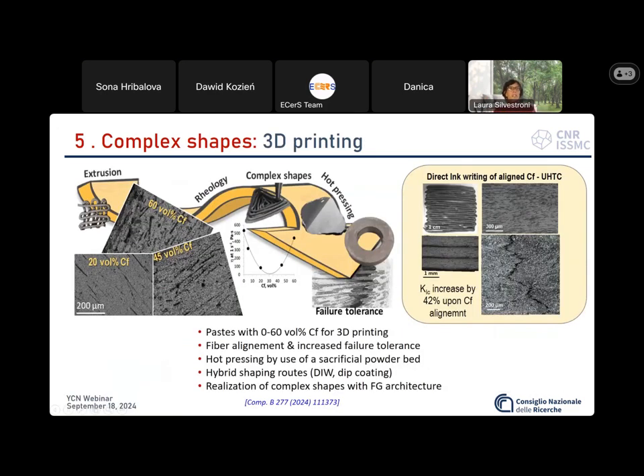The last comment is on additive manufacturing, which has become a very popular and convenient approach in the last years. By direct ink writing, it is possible to extrude UHTC-based paste, also containing fiber, and create a plethora of complicated shapes. There are several cool aspects related to this technology, like, for example, we can add up to 60% short fibers for 3D printing. We can align the fiber and increase the failure tolerance and the fracture toughness. We can even hot press such a